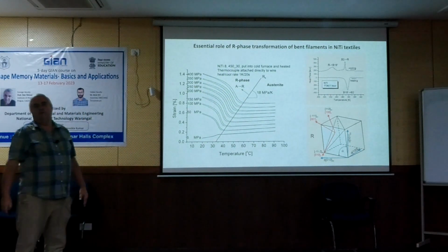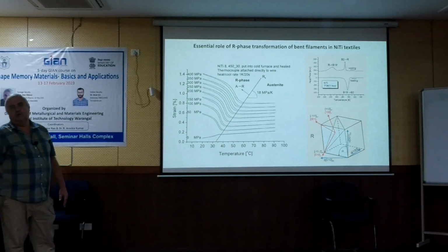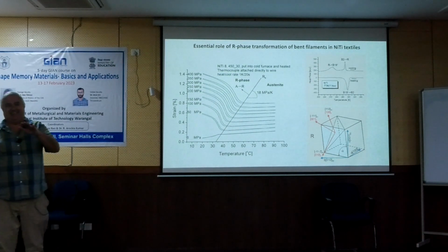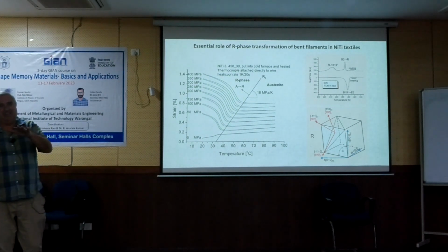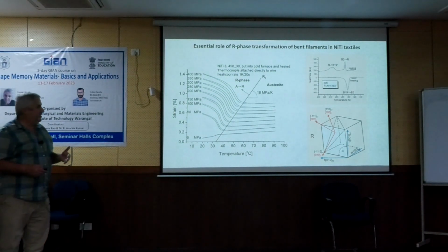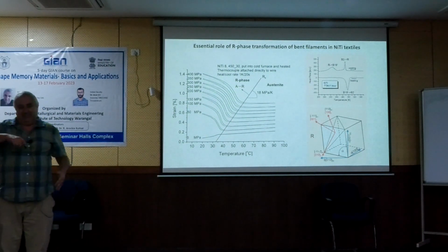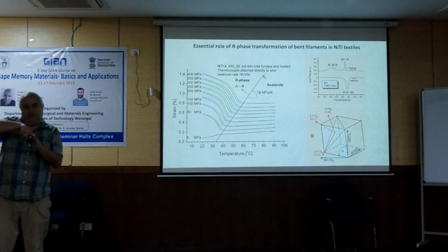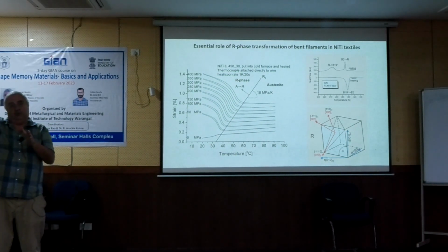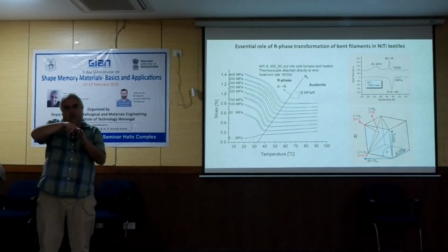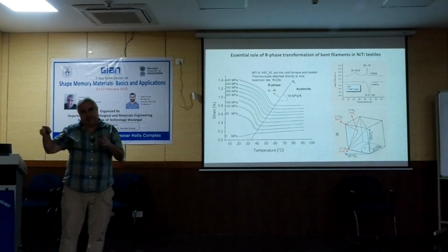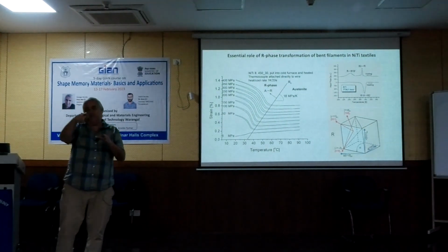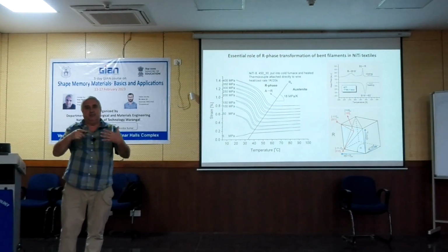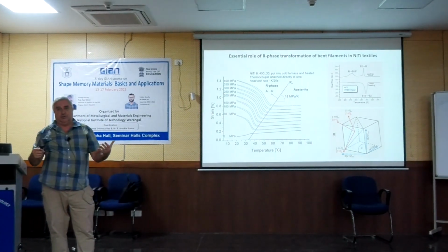On the stress-strain curve for this Nitinol wire, how can we characterize the R phase transformation? Well, I'm sorry, we discussed this before. If I go back, like R phase transformation, you remember in the stress-strain curve, you have the elastic modulus, and if it's R phase, the modulus is low, or there is some kind of S shape. The same upon cooling under stress. It always precedes. You have at first R phase and then the monoclinic transformation. So it's sometimes called pre-martensitic transformation. You see it always before.